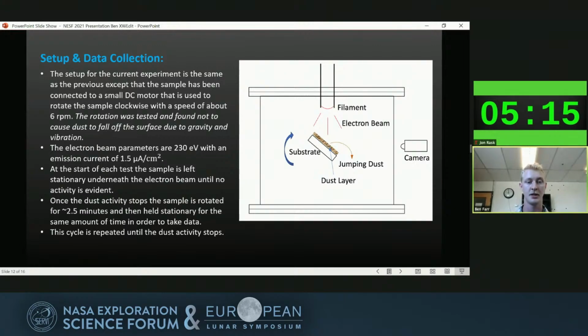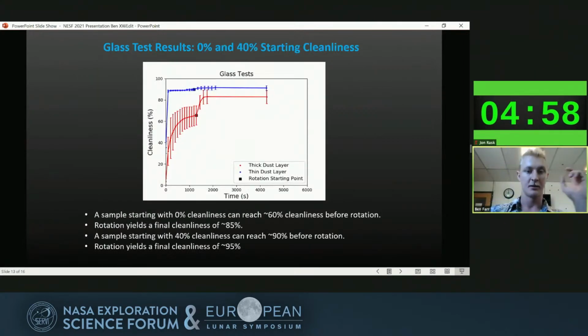The only thing that we changed for this experiment was that we attached the sample to a DC motor that rotated it at 6 RPM. We would rotate for 2.5 minutes, exposed to the beam, and then stop for 2.5 minutes. In that 2.5 minute pause, we would take our data. We tested glass first. For every test, we would let the process go without rotating. Then once it stopped, we would start rotating so that we could see exactly how much the rotation helped.